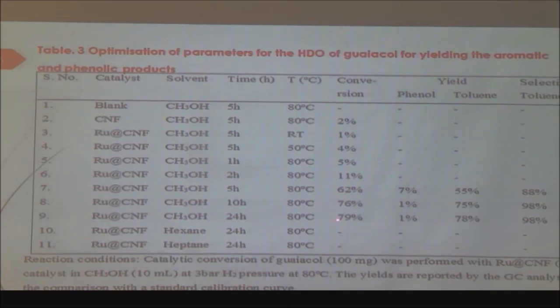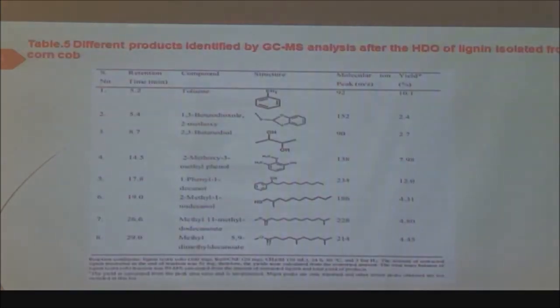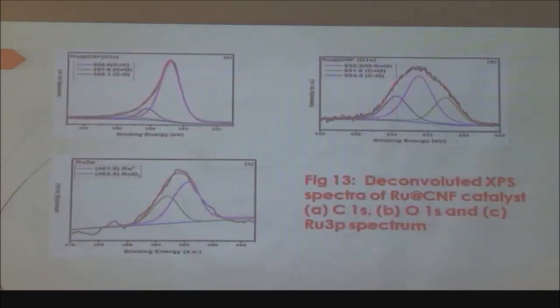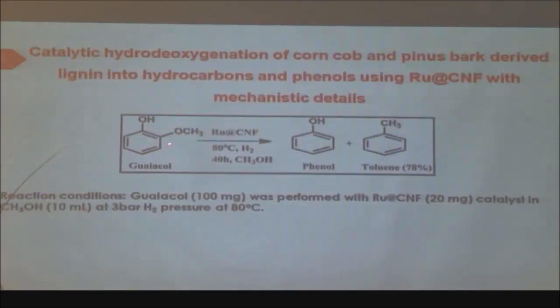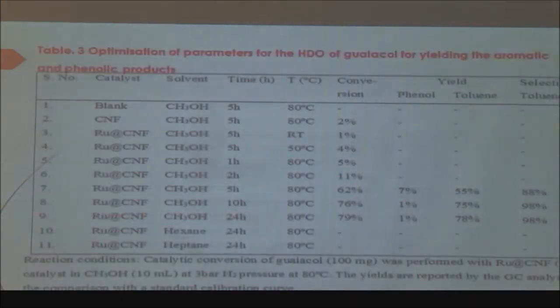So the maximum conversion was 79%, where toluene was 78%. If you see the reaction, this is the reaction. When the toluene is generated, it means the OCH3, the methyl oxygen, is removed, and this OH is removed. See here, a very, very good thing is happening. It is removing all the oxygen linked to it and making the hydrocarbon. So we were very excited from this result, and we wanted to see what would happen on lignin.